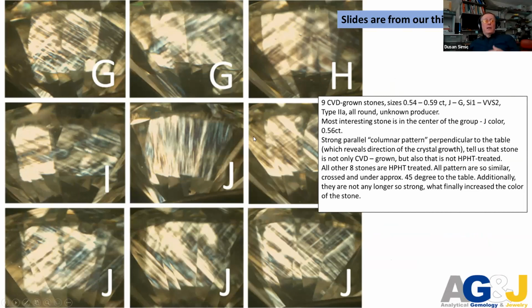So right now, let's go to HPHT treatment of laboratory-grown diamonds. This is an interesting slide, and you will find this in our book. In the middle, this J color is an as-grown CVD diamond, with interesting birefringence perpendicular to the growth direction. This stone is not HPHT treated. But how they are treated today, for less money, like a cheap treatment, you will get this result where all these structural defects went to the 111 plane.